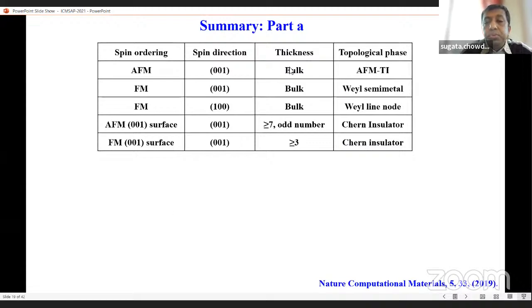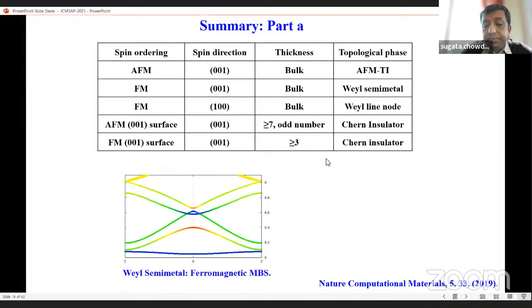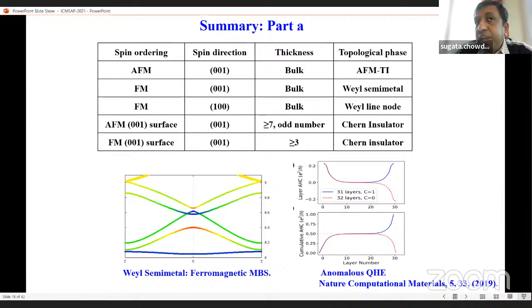So here we put all those cases together. For the antiferromagnetic bulk, it is an antiferromagnetic topological insulator, but the bulk is a semi-metal depending on the direction of the magnetic field. On the other hand, when the antiferromagnetic system is seven layers or more, it is a Chern insulator, and when it is three layers, the ferromagnetic surface gives a Chern insulating phase. That way we can conclude that the manganese bismuth telluride structure is a very good candidate for observation of the quantum anomalous Hall effect.